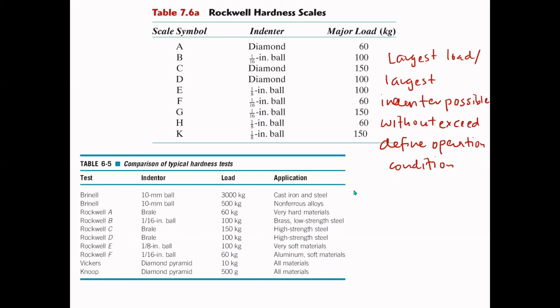a test sample or the tester during the loading application from a condition such as dirt under the testing specimen or on the elevating screw. It is also quite important to keep the surface finish clean, and decarburization from a heat treatment should be removed to ensure that the hardness value that we get is precise.